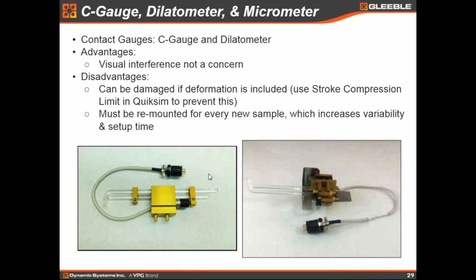The other disadvantage, as Brian mentioned, which can be a little bit of a nuisance if you're running a lot of tests, is that you have to remove the gauge and then remount it every time for every new sample, which increases the setup time some. Once you have everything else set up, it doesn't take a whole lot of time, but it's not as convenient as not having to replace it. And it can increase the variability if you run 100 tests and you're not watching it so closely. There's a little bit of variability potentially in that.